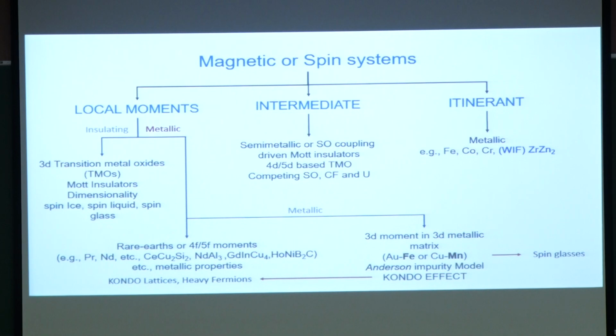So, in local moment systems, as the name suggests, the unpaired electron that gives rise to the magnetic moment is localized at a lattice site, whereas in the itinerant case the situation is more complex. So, these materials often exhibit metallic behavior. In the local moment case, you have mostly an insulating ground state, but then there are exceptions, and you can have local moments in metallic rare earth compounds. For instance, here where the rare earth moment is highly localized, and there is a reason for that, because the 4f shell is pulled towards the nucleus, and it is well shielded by 5p and 5d most likely electrons, and therefore they retain their local moment.